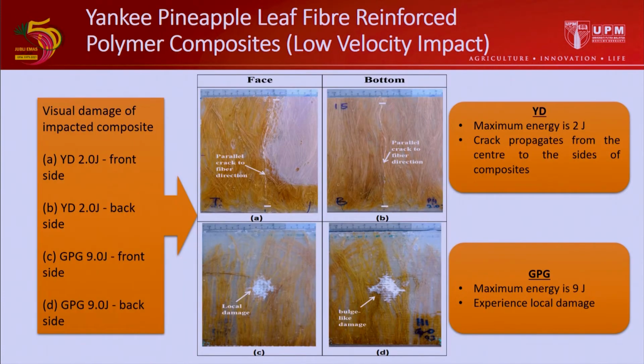Pineapple composites and pineapple-glass hybrid composites were evaluated in low velocity impact testing. The results show that the non-hybrid pineapple composite is able to hold up to 2 joules of impact energy, and beyond this impact energy, the composite breaks. The hybrid pineapple-glass composite shows superior impact resistance compared to the non-hybrid due to the presence of woven glass fiber on the top and bottom part of the composite that helps in resisting the impact. The pineapple-glass hybrid composite can withstand impact energy up to 9 joules compared to 2 joules for non-hybrid composites.